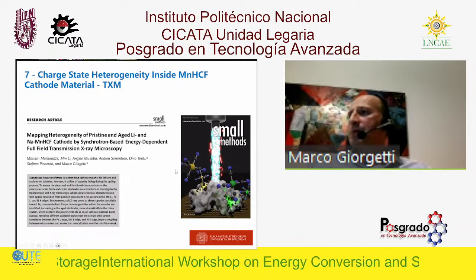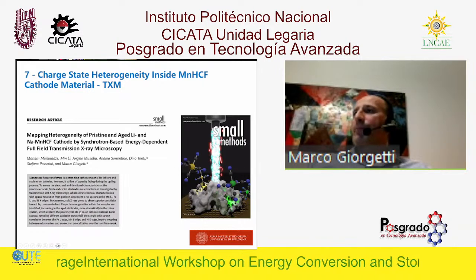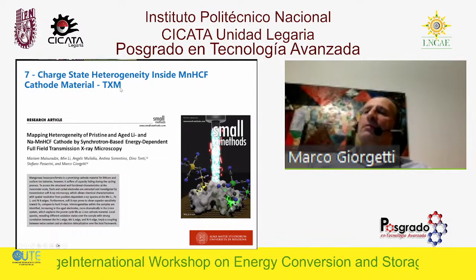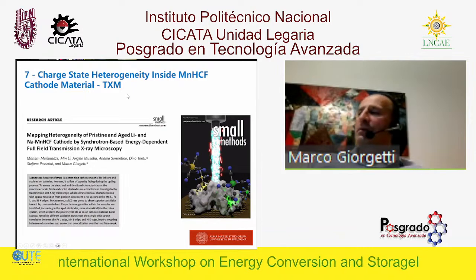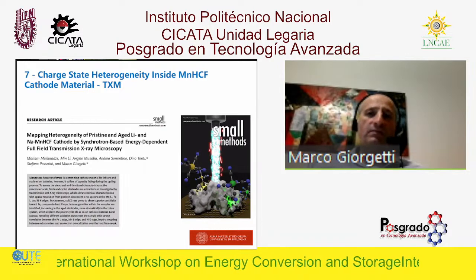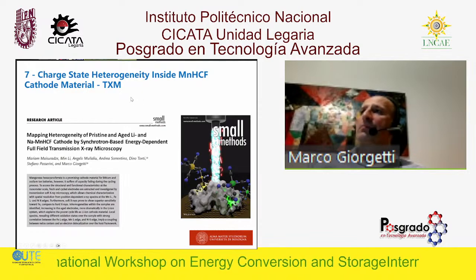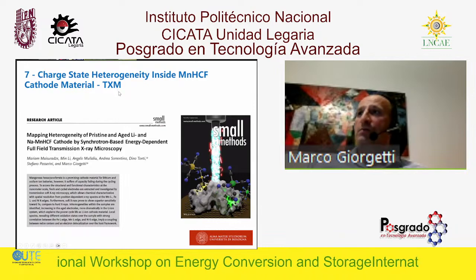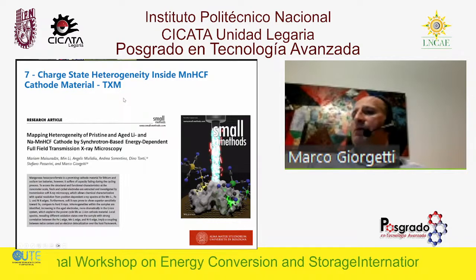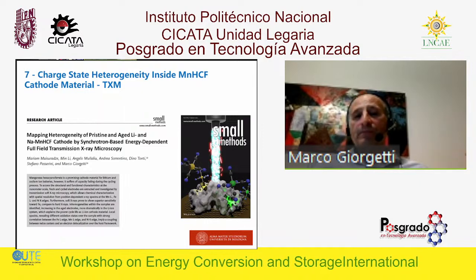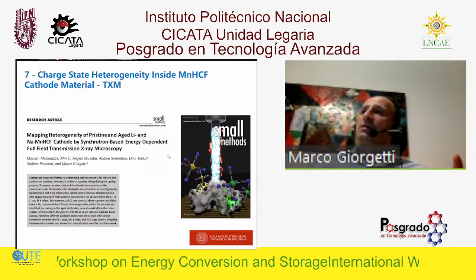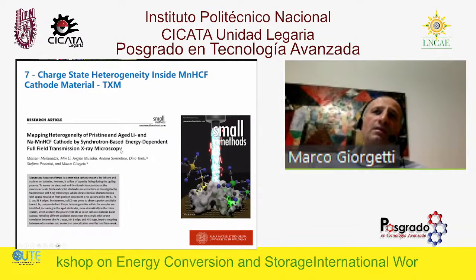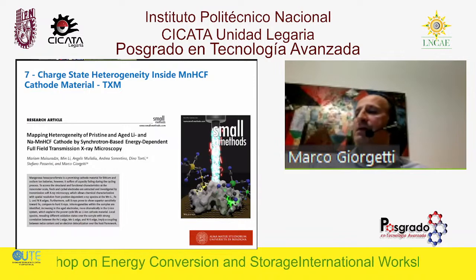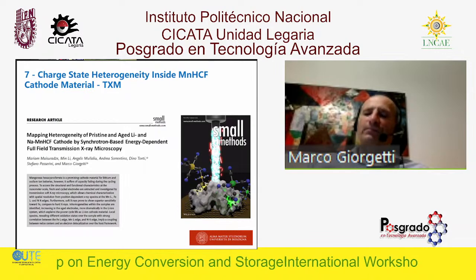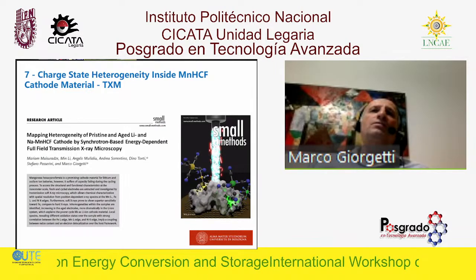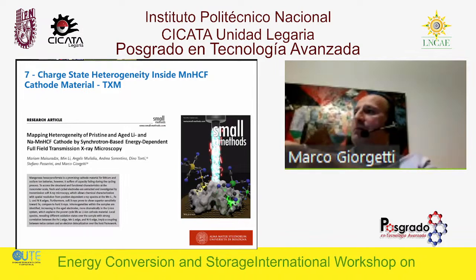This paper has just been accepted. And why do transmission X-ray microscopy? Because of course you can do it with the TEM. While with the TEM you have an electron beam that is very destructive to the material. So we adopted this X-ray microscopy at the synchrotron, especially because of that. Of course, the spatial resolution in this experiment is not as good as in electron microscopy, because an electron beam can be more finely tuned with respect to an X-ray beam.